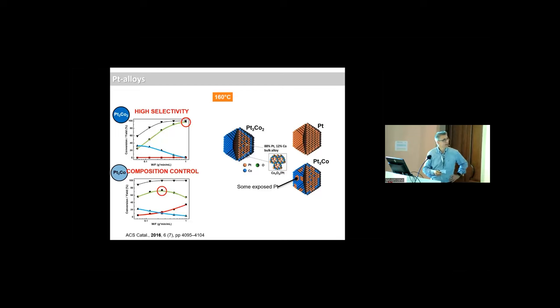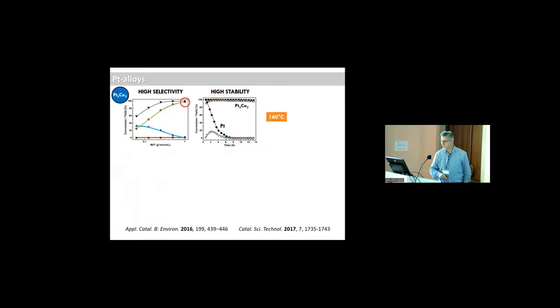And why is that? You absolutely need to cover all the surface with cobalt. And this is a peculiar reaction because cobalt is not active, but still you can activate hydrogen in the sublayer and still perform the hydrodeoxygenation reaction. But if you have some patches of platinum exposed, as proved by near ambient pressure XPS, EXAFS, and different techniques, you have poor selectivity. Of course, cobalt has ethical issues.